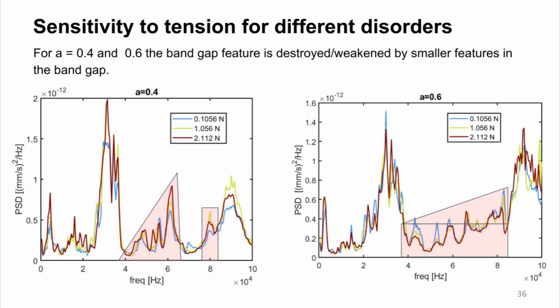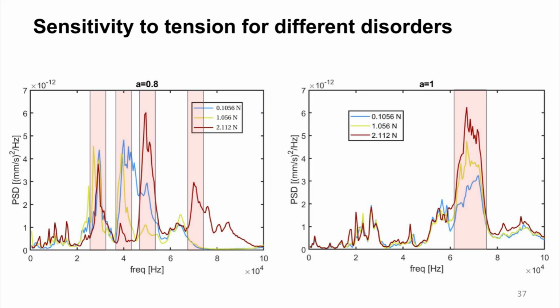For higher perturbation of 0.8, and we have already seen this curve, it does depend on tension, and different peak features in the power spectral density curve have a different kind of dependence on the tensions I've tried, and some of these features are highlighted here. Some of these features are not present across multiple different tensions, whereas others are present and do agree, whereas some others do not agree.